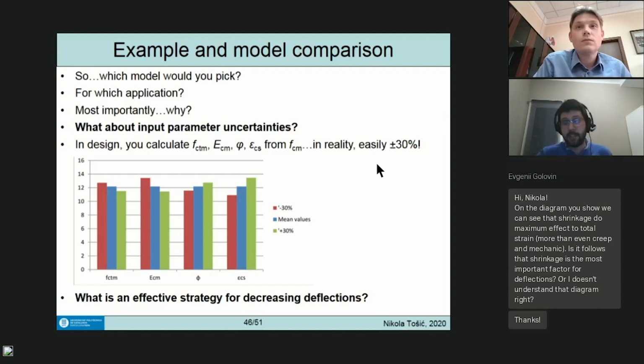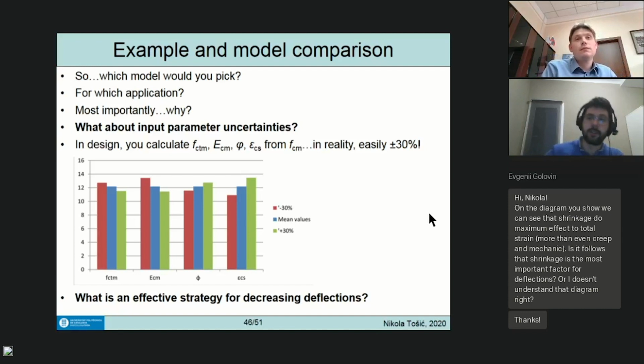So it's very important to take this into account when dealing with slabs and in-service behavior close to the cracking load. Do a sensitivity analysis for at least tensile strength - in the codes you have lower and upper characteristic values which are 30% different, so do a calculation to check where you stand. And not to mention creep and shrinkage - in the codes you also have characteristic values, and the differences are even more than plus minus 30% because they can be huge.